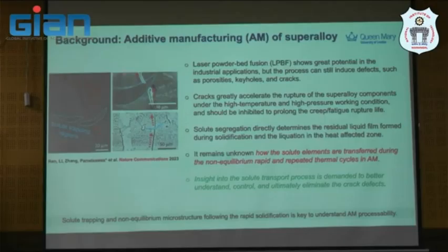This is another curiosity that we have. And then we know that the crack greatly accelerates the rupture of superalloy in high temperature conditions. And this segregation basically determines the liquid film formed during solidification, the solute segregation and liquefaction in a heat affected zone. Something that remains unknown is how this solute transport of elements occurs during non-equilibrium rapid and repeated thermal cycles. Because we don't know why it's actually trapped at the bottom of the melt pool. This is the question we ask ourselves, and insight into this transport will provide a better understanding, hopefully to eliminate crack defects, because if we know this has an impact on the crack propagation, we can do something to mitigate that. And that's what we are trying to do too. We believe understanding solute transport here will be key for additive manufacturing processability.